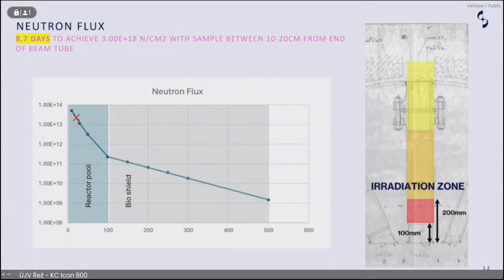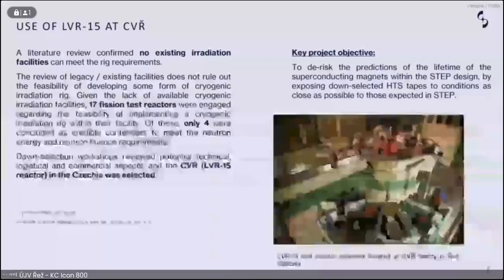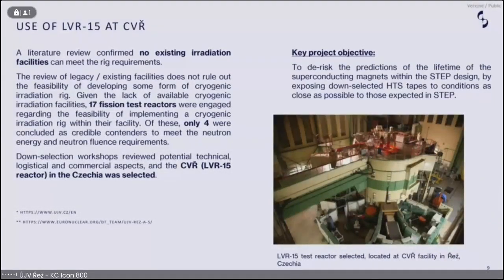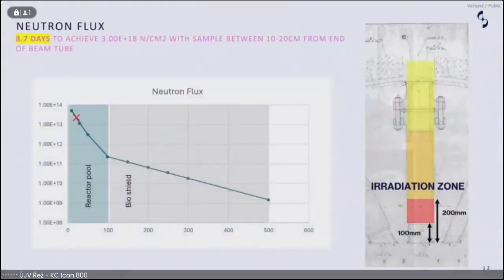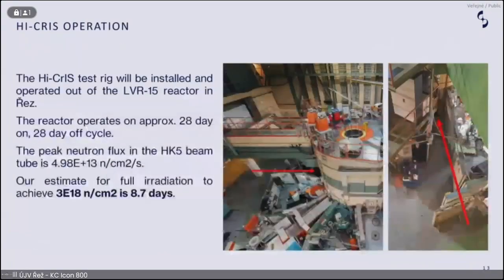This is where CVR is perfect because it has these horizontal channels - it's a user facility. So what we've done is looked at how we can maximise the use of the irradiation campaign and the rig for the amount of data we can get from this. Through this we've identified that between 10 and 20 centimetres from the end of the reactor channel is where we'd ideally like our sample to go. Theoretically, we should get the total irradiation after about 9-ish days, but the reason I say 9-ish days is because I now move on to the experiment itself.